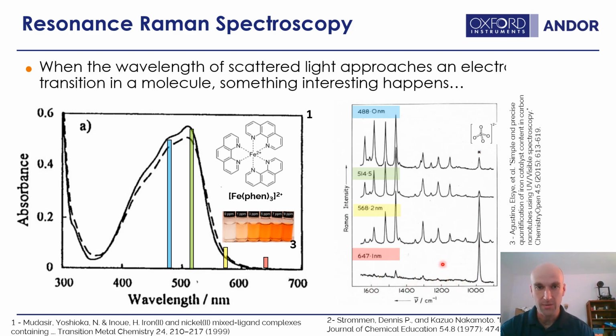And then as we go closer and closer to resonance, and we're on resonance, all of a sudden, relatively, and this is scaled, normalized, the Raman spectrum from our compound has become very, very, very bright. We've had quite a bit of enhancement. So not only have we had different bands come into play, and I think you'll see it a little more closely next time, but different bands getting enhanced more than others, we have a general enhancement. So let's talk about this more in a second.